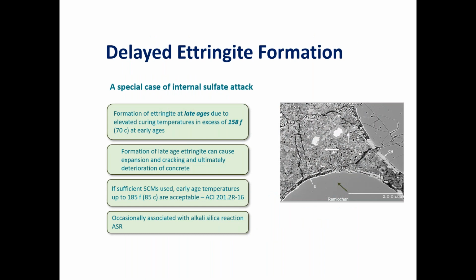Okay, I said we were going to do it, so let's do it. We have delayed ettringite formation, and again, I don't want to scare anybody off. I have been a producer of concrete for many years, as well as somebody who services and supplies cement to concrete producers, and I have yet to have one of these problems come up, or if it has, it has not been identified as DEF. But again, like I was saying earlier, delayed ettringite formation is a late formation of ettringite, and it essentially happens when you have initial curing temperatures in excess of 158 degrees. Now that's for an OPC, an ordinary Portland cement type mix.